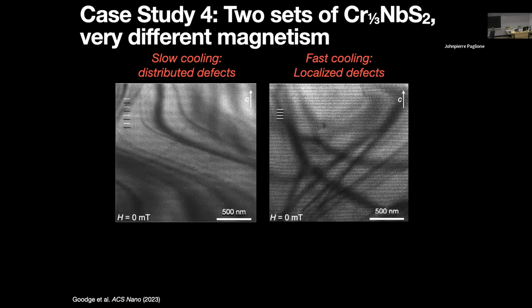Have you done any attempts, instead of slow cooling through where you expect the 2x2 phase to form, to estimate what temperature you expect that to be stable, and just quickly drop from your synthesis temperature to that temperature, and then let it anneal there? Yeah, we've done so. We spent the fall doing experiments like that. It works. So it certainly is very easy if you have a stoichiometry of 0.25, and say you go to a crystal, and it looks like it has mostly 2x2 by Raman spectroscopy.